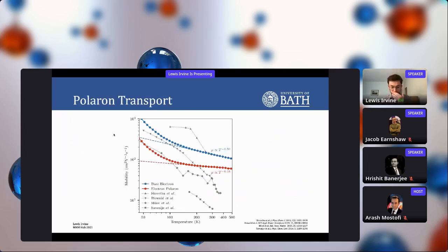So these are the mobilities that we calculated. First of all, in the blue here, we have the standard bare electron band results. You can see that the temperature dependence tends towards T to the minus 0.5, as you'd expect. And then when we add in the polaron terms, so all we have is the new rates and the large effective mass, you can see the effective mass has led to the mobility overall dropping by about a factor of 2 when it gets to room temperature.